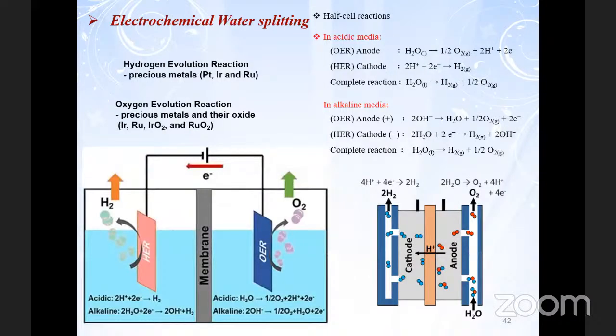But if you come to electrochemical water splitting, two reactions are involved. One is the hydrogen evolution reaction, the other is the oxygen evolution reaction. Similar to the fuel cell, here also the problem is the highly expensive precious metals. Platinum, iridium, and ruthenium are usually used on the cathode side. And on the anode side, in the oxygen evolution reaction, again iridium, ruthenium, or their oxides are used. So what happens at the OER, for example, is that this precious metal or its oxide splits the water, and the H plus passes from the anode to the cathode, and at the HER it produces the hydrogen.